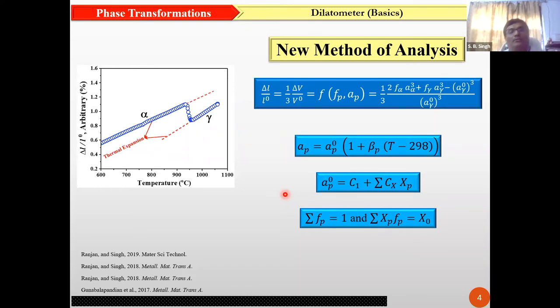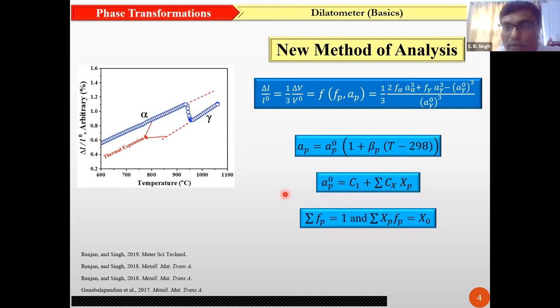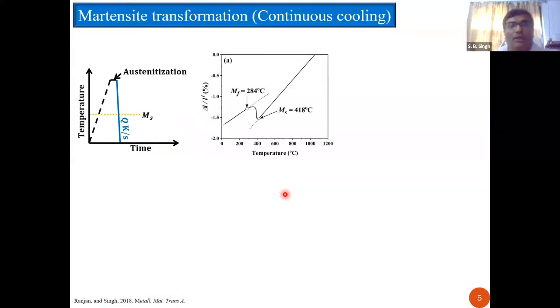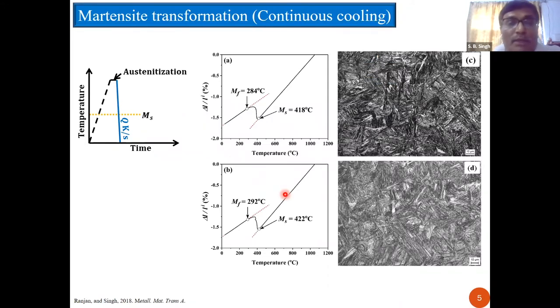We have done this for all transformations we see, for example during austenite formation from pearlite or during cooling. The first transformation I would discuss is martensite. When austenite is cooled rapidly enough, it will transform into martensite. This is straightforward because the parent phase and the product phases both have the same composition, so there is one less variable to deal with.